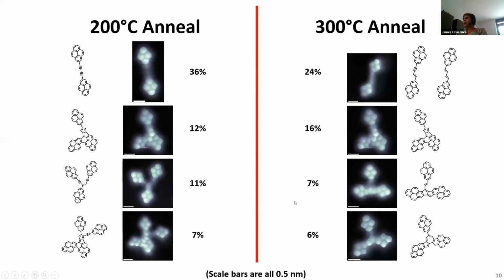Now, if we go to 300 degrees, we see some of the same products like this fused trimer. We also see these dimers here, which are no longer straight, but have this offset, indicating either one or two double bonds between them, as well as some of the products here at lower coverages, lower incidences.